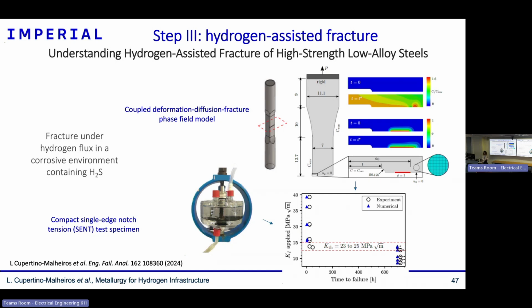But BCC steels, it diffuses out quite quickly, which for this test was good because I only want to test trapped hydrogen. But if you want to test your whole hydrogen, pre-charged tests for BCC steels might not be a good option. You need in situ tests, just because a great part of hydrogen can leave your sample before you start the test. So more realistic tests will be in situ.